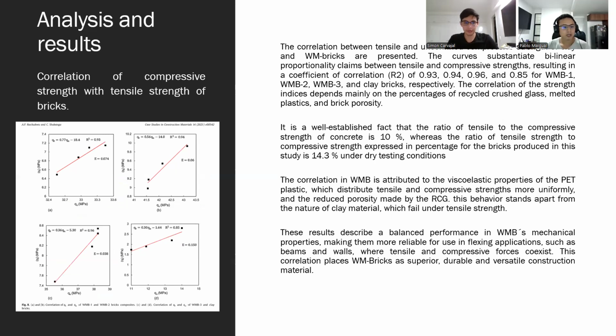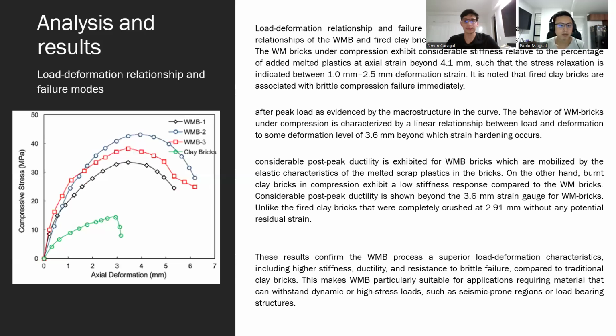Okay, correlation of compressive stress with tensile test on bricks. The correlations between tensile and unconfined compressive stress of clay and WM bricks are presented. And the correlation in WMB is attributed to the viscoelastic properties of the PET plastic, which distribute tensile and compressive stress more uniformly. The results describe a balanced performance in WMB's mechanical properties, making them more reliable for use in flexing applications. And load deformation relationships and failure modes.